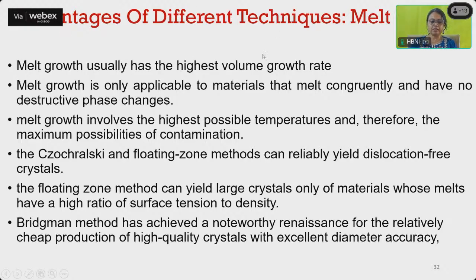first is the advantages of melt growth. Melt growth usually has the highest volume growth rate. I'm talking about silicon crystal growth. You can imagine a silicon crystal of 12-inch diameter. 12 inch is like 1 foot. That much diameter single crystals of silicon can be grown, with a length of 3 meters, 3 meter high and 12 inches diameter. Single crystals of silicon are grown in the industry today using the melt growth technique of Czochralski. So this has got the highest volume growth rate.